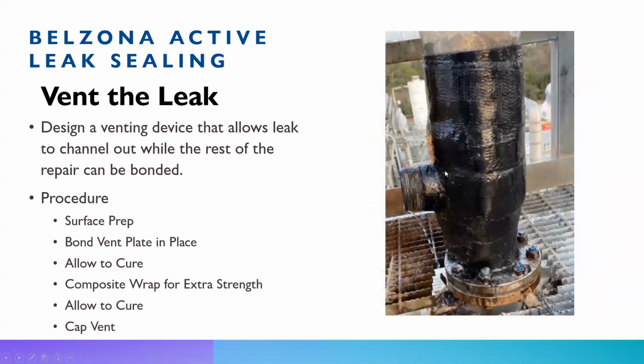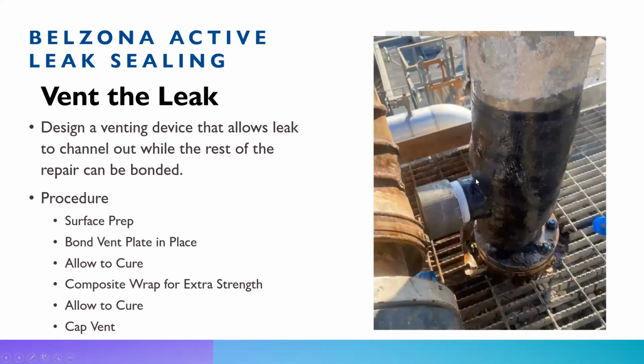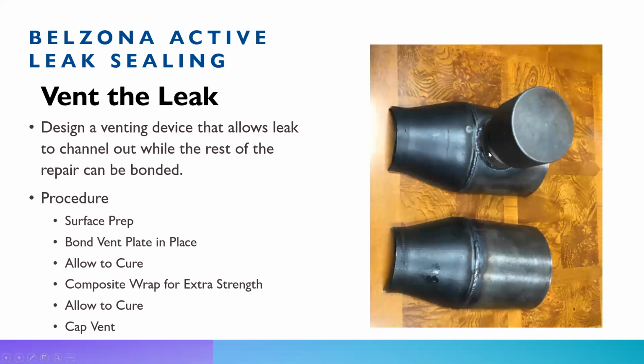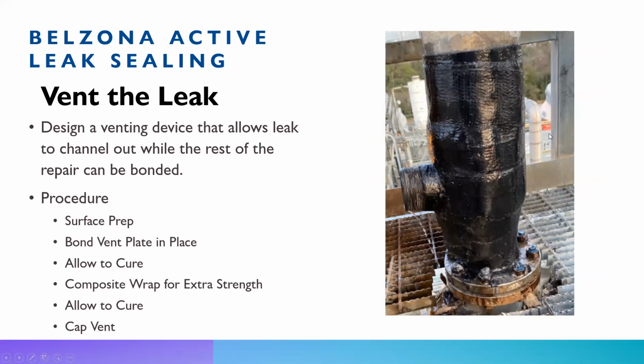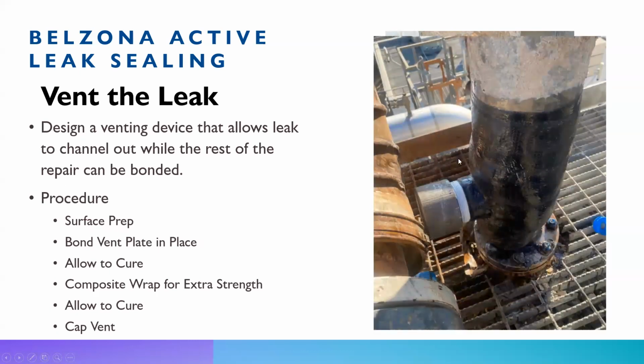So here we were dealing with a tough geometry. We were dealing with a 4-to-6 reducer. We had a large hole here. So we aligned this plate so that the orifice here, the threaded nipple, was lined up right over the hole. We bonded it down with our surface tolerant product, wrapped it, allowed it to cure. All this time, you can see the leak is dripping out. So we're not putting any force on the repair. We're allowing it to cure while the leak is venting. So basically, there's no pressure being put on the repair. Once everything's cured, you cap it off.